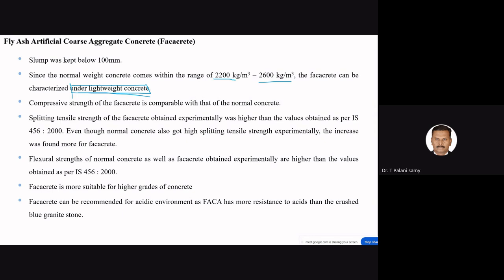The compressive strength of the concrete is comparable with that of a normal concrete. The split tensile strength of the concrete obtained experimentally was higher than the values obtained from IS codes and all those things. These are some observations. Then the concrete is more suitable for higher grade of concrete also. We proved that the concrete can be recommended for acidic environment. In an acidic environment, the faca has more resistance to acids than the crushed blue stone aggregate. This we need to study in the long run, how it works and all.